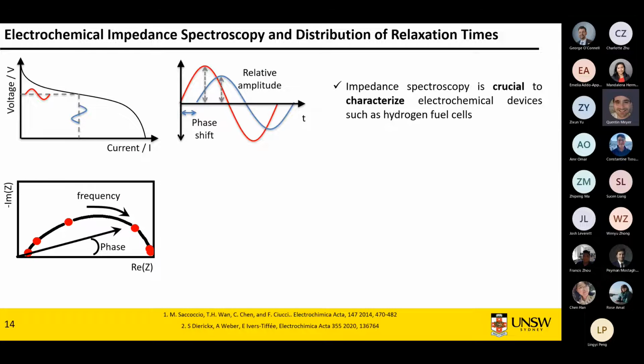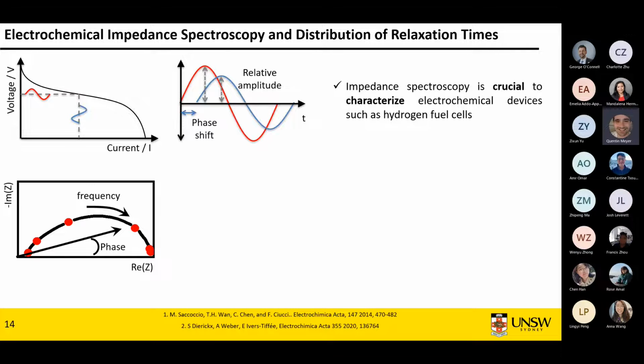But now, another technique that I work a lot with is impedance spectroscopy, using distribution of relaxation times. What EIS can do for you is basically you impose a small perturbation of current, and you record a small voltage response. You do this at one frequency, you get a phase shift and magnitude signal, and you go, okay, now I'm going to try the next frequency. You keep on doing this, and you get what's called a Nyquist plot. The problem that many people have with Nyquist plots, and I've faced it many times, is that it's a bit like a black box.